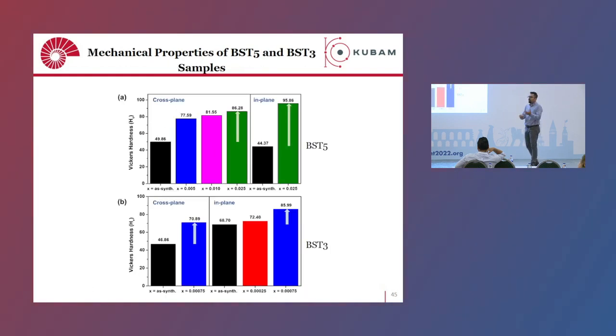In addition to the transport characteristics, it is better to also check the microhardness, or the mechanical properties of these materials, because for module applications we want durable materials. Here you can see the synthesized materials. They are black. This is bismuth 0.5, and this is bismuth 0.3. When we add copper telluride, in the cross-plane or in-plane direction, for both cases we see a substantial increase in the microhardness, the mechanical properties of this material.